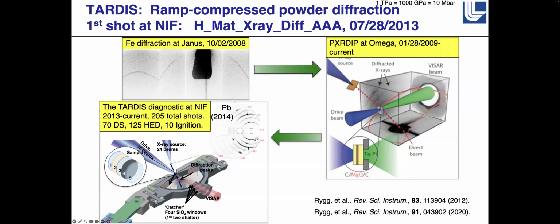And we very rapidly, by January of 2009, so in just 3 months, we built what we call the PXRDIP, the powder X-ray diffraction image plate system at Omega, where we just built a box out of tantalum this time, where we put image plates on the inside of it. We have this pinhole with the sample sitting on it here. And this shows the diffraction and how we get it. So you can see we get a direct through down on the bottom here, and we can see diffraction on the three other image plates.